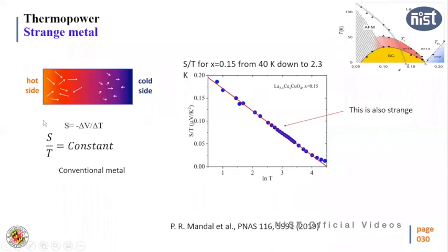Now, as we have seen that S, this thermopower, S is proportional to T. So S by T basically should be constant in conventional metal. But what happens in this strange metal, this S by T is not constant. It is some sort of logarithmic. It doesn't show conventional metal-like behavior. This is also again strange. This S by T logarithmic behavior is seen down to 2.3 Kelvin, from 40 Kelvin to 2.3. So I just want to remind you that all these properties we are talking about at low temperature. Low temperature means below 40 Kelvin or below 20 Kelvin. So below 20 Kelvin or below 30 Kelvin or 40 Kelvin, this should be the behavior of conventional metal. This one was published in PNAS.